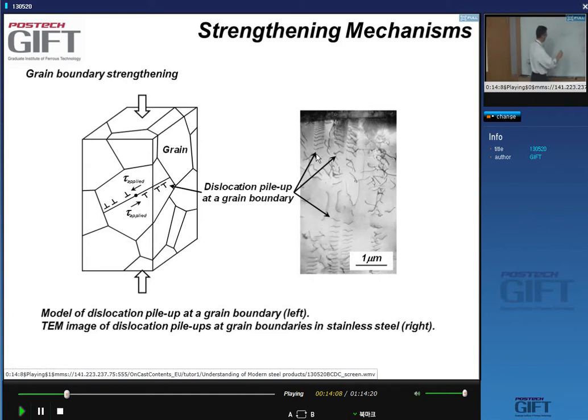Now, the way you have to see the creation of a pileup is as follows. So say this is a grain boundary here, and this is a glide plane. So here, for instance, there is a dislocation source that emits dislocations, loops of dislocations. And these dislocations, so here you have successive dislocations. They arrive at this grain boundary. And so say this dislocation is stuck there.